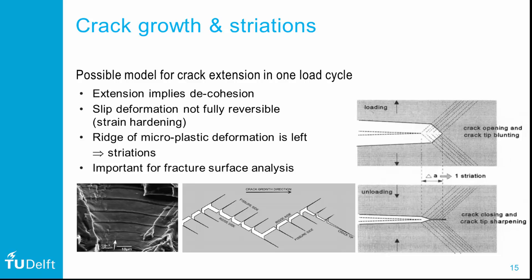The crack propagates generally perpendicular to the principal stress by a mechanism in which deformation occurs along multiple slip systems. The slip systems illustrated are at the location of maximum shear, and their deformation will cause the crack to increment. This slip deformation is not fully reversible due to strain hardening; hence, during loading and unloading, little microscopic plastic ridges will be formed while the crack increments.